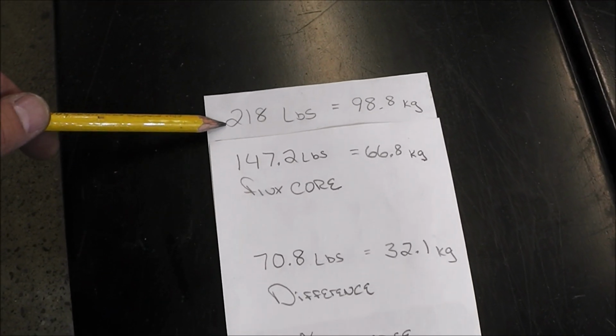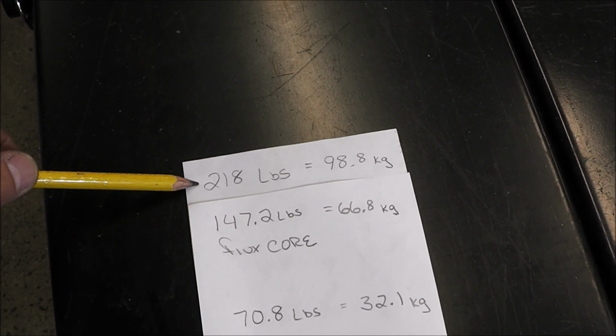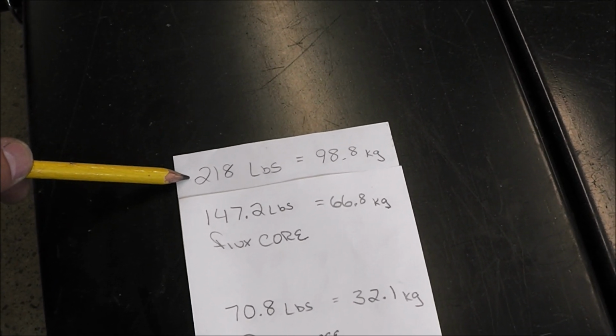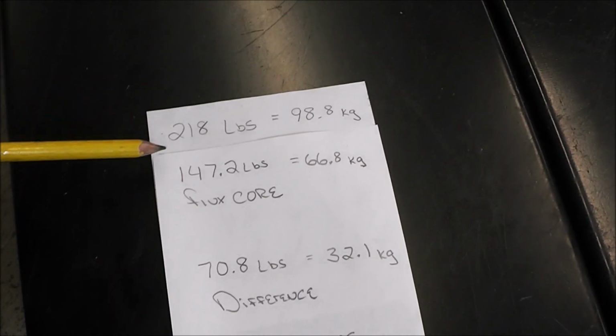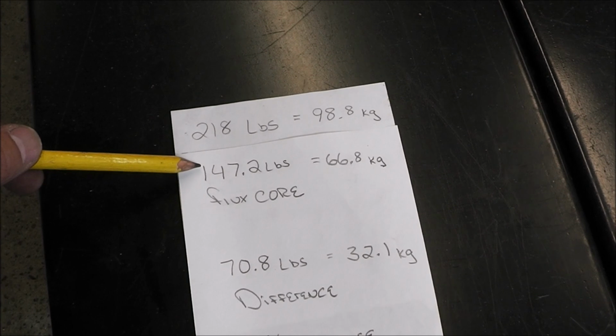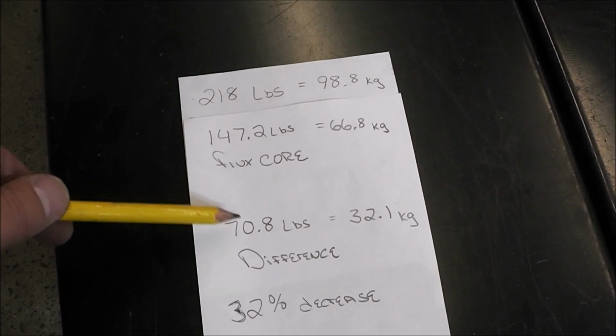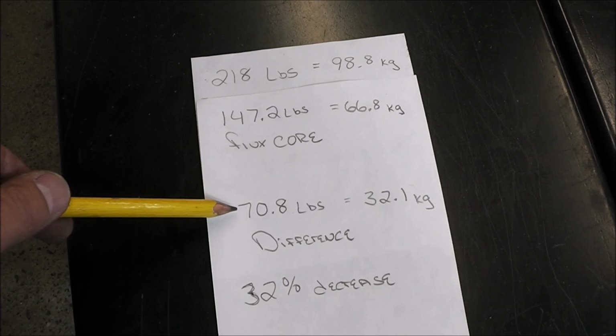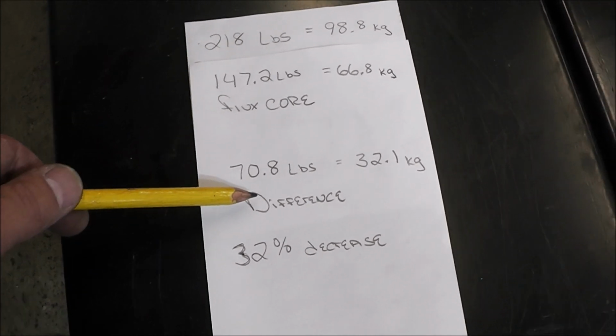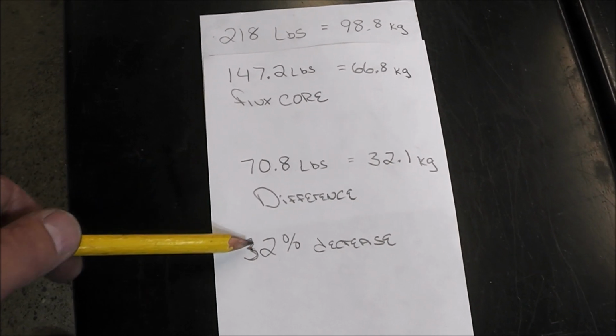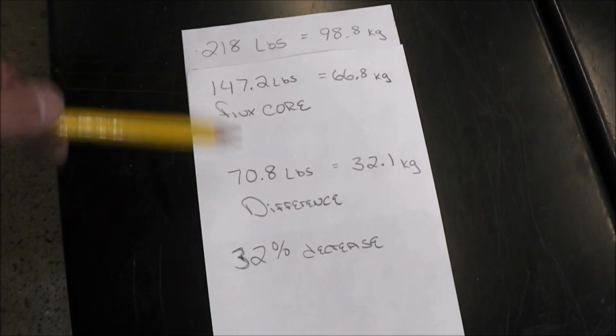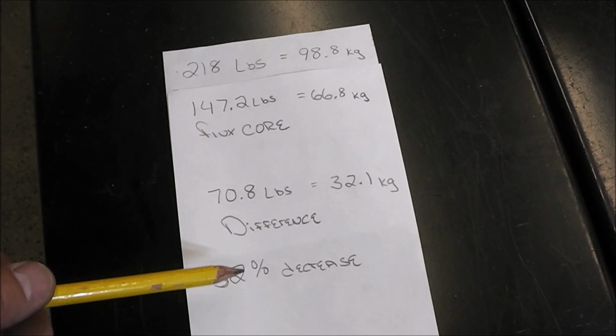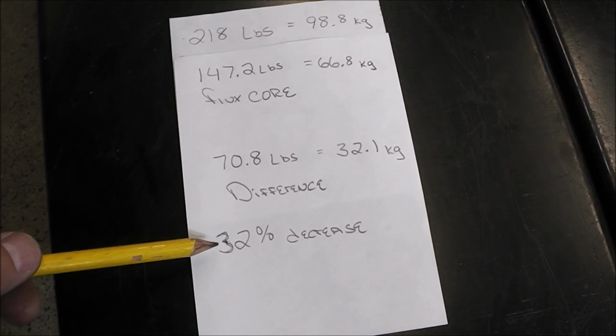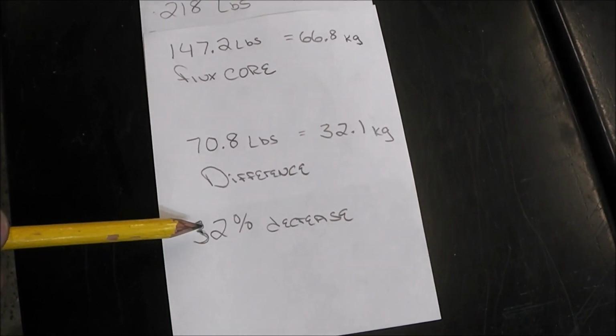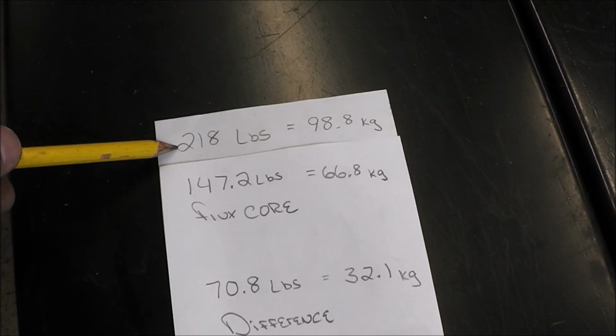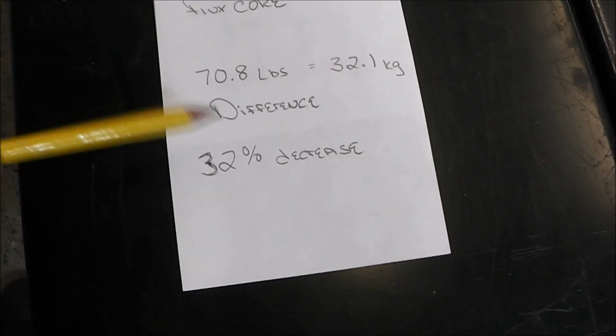So the original pan handle, before we did any repairs, when it was all intact, took 218 pounds to break. Here's all the kilogram figures. Flux core broke at 147.2. So the difference between the two is 70.8 pounds, which is a 32% decrease. So if you are going to weld a cast iron pan using flux core, it's going to be 32% weaker than the original part before it broke. So there is a difference.